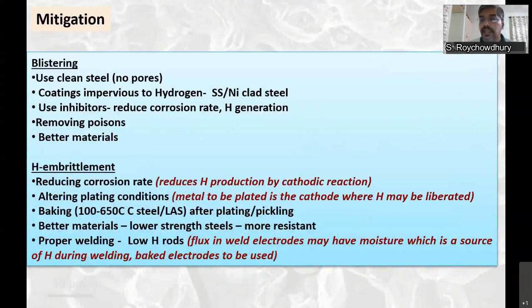So mitigation: blistering you can avoid by avoiding pores. Use clean steel so that you do not have any pores inside. If the steel is clad by stainless steel or nickel, which is impervious to hydrogen, then hydrogen will not be picked up. Reduce corrosion, and hydrogen generation will be reduced. Remove poisons like arsenic and antimony in the environment, which will reduce hydrogen pickup. Use better materials. Higher the strength of the material, more prone it is to hydrogen embrittlement or hydrogen damage. Softer, low strength materials have better resistance to hydrogen damage.